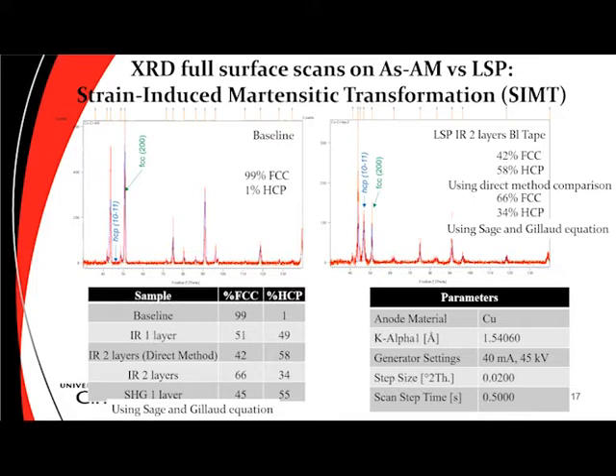Also, an interesting finding of the laser peening on the cobalt-chromium-molybdenum alloy can be seen here, where starting from the baseline material, which was usually made up of approximately 99% FCC and just about 1% HCP, after laser peening, there was a phase transformation as seen here. The different laser peening conditions cause strain-induced phase transformation, creating around 50% HCP phase at the surface.